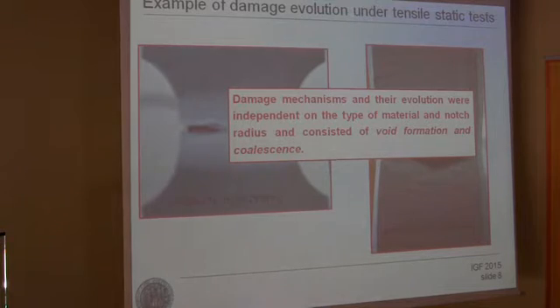This type of observation was carried out for all materials analyzed and for all the notches, and we can conclude that the damage mechanism and its evolution were independent of the type of material and notch radius, and consisted in void formation and coalescence at the crack tip.